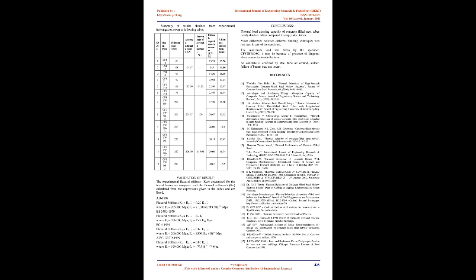Conclusions. The flexural load carrying capacity of concrete-filled steel tubes nearly doubled when compared to empty steel tubes. Much difference between different bonding techniques was not seen in any of the specimens. The maximum load was taken by specimen CFSTB-WDSC, it may be because of the presence of diagonal shear connectors inside the tube. As concrete is confined by the steel tube all around, sudden failure of beams may not occur.